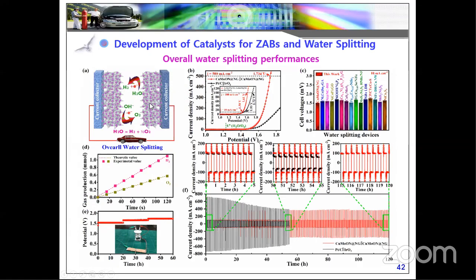So from the ORR and OER properties, we fabricated the zinc air battery, but now from the HER and OER performances, we fabricate the water splitting devices. In the water splitting device, because both electrodes use the same catalyst as a bifunctional catalyst, we achieved 1.5 volts compared to the conventional catalyst. Our catalyst has better cell voltage performance compared to the reported materials. We also performed hydrogen evolution and oxygen evolution with almost similar theoretical values. And the rate reversibility, I already explained the 24 hours reversibility.